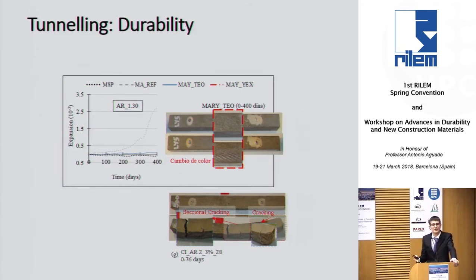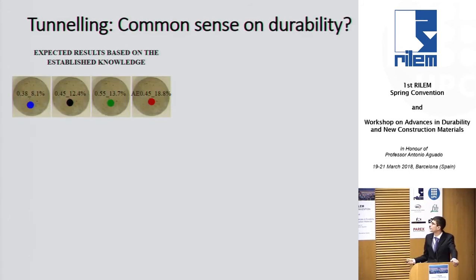We have also tried to change the cement mix to reduce this likelihood. So this is an equivalent mix here. The only change is that we added, in this case, a little bit more gypsum in the mix to reduce the content of AFm. And we saw almost no expansion or very low expansion and no cracking in comparison with the equivalent. So it's very easy to control this phenomenon, right?